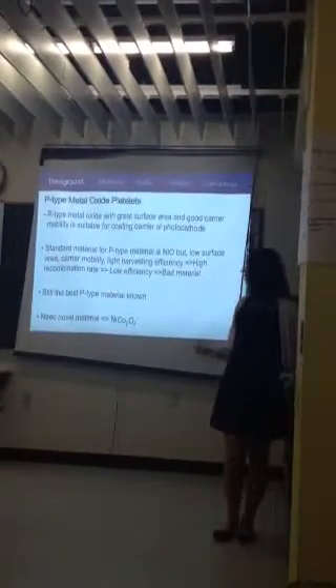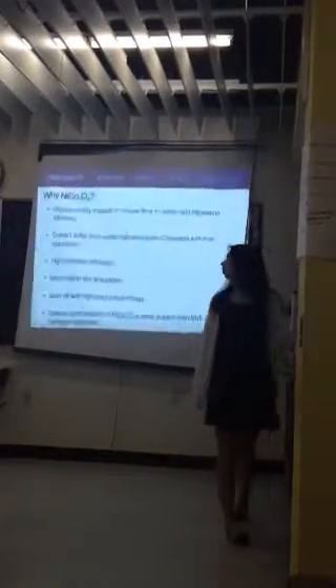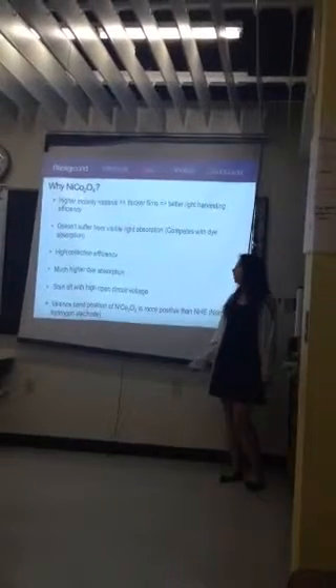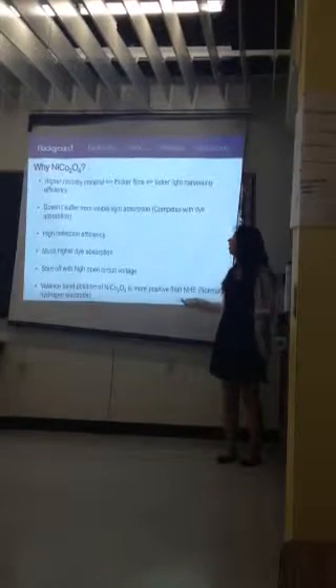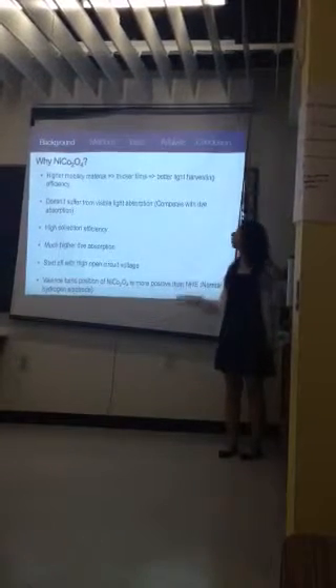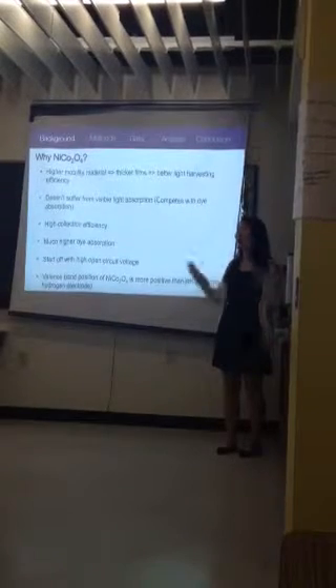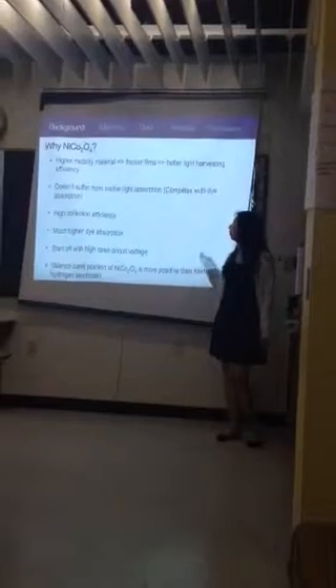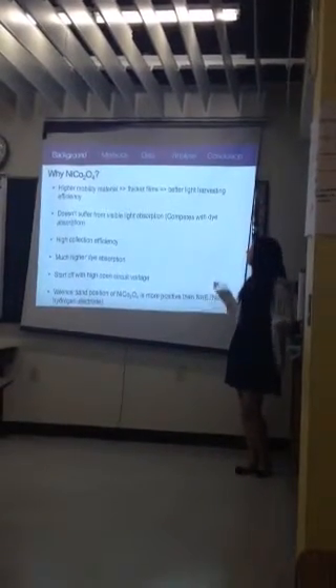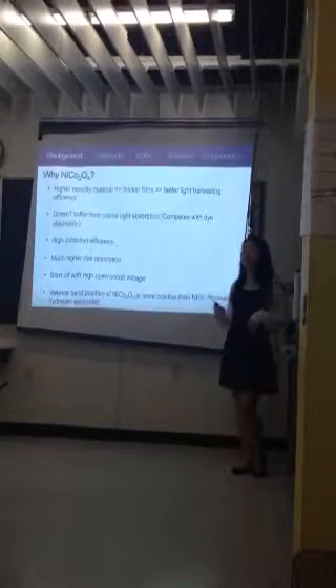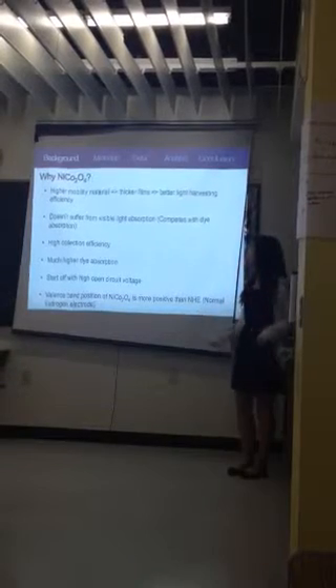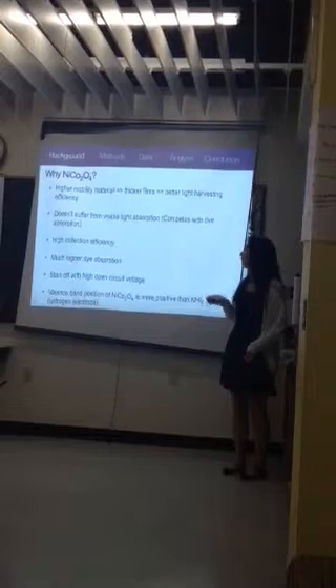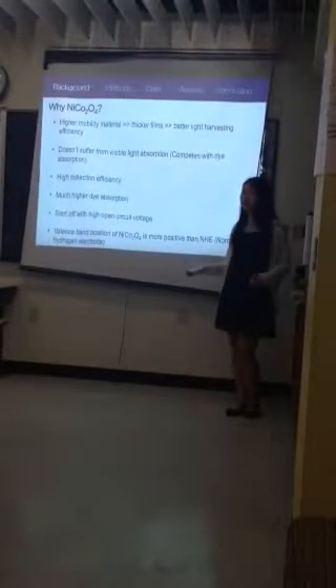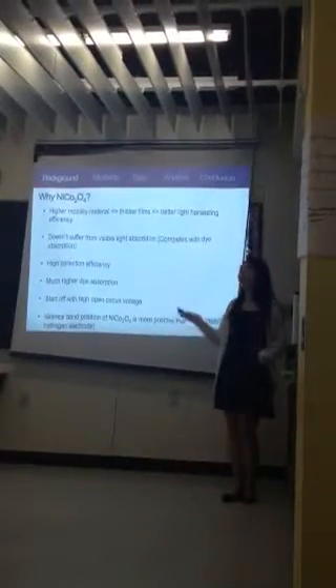Therefore, we are in search of a new material to replace nickel oxide, and the material we found is nickel cobalt oxide. Why did we choose it? There are many reasons. First, it has higher mobility, which allows us to coat thicker films. We can load more dye on it, leading to a better light harvesting system and more current produced. Also, it doesn't suffer from visible light absorption, which nickel oxide does suffer from. That absorption competes with dye absorption, so it lowers the efficiency of current production dramatically. It also has much higher dye absorption, and one really nice thing is that it starts off with a high open circuit voltage, so it starts at a better start line than nickel oxide does.